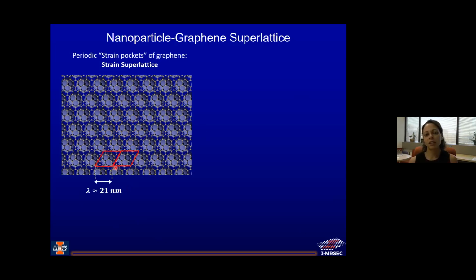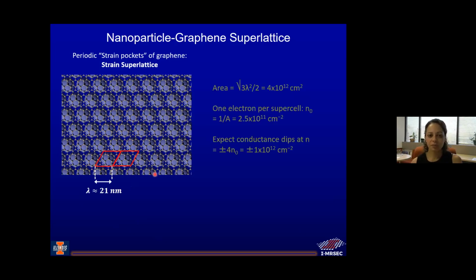And so here I'll talk about the 20 nanometer nanospheres. And so our lattice is 21 nanometers, giving them a little space in between them, right? But basically they're touching. So a 21 nanometer superlattice spacing there. Okay, and I just do a very simple calculation, right? You take the area of each of these red things, which is equal to 4 times 10 to the minus 12 centimeters squared. And if we assume that we have one additional electron per supercell, right?